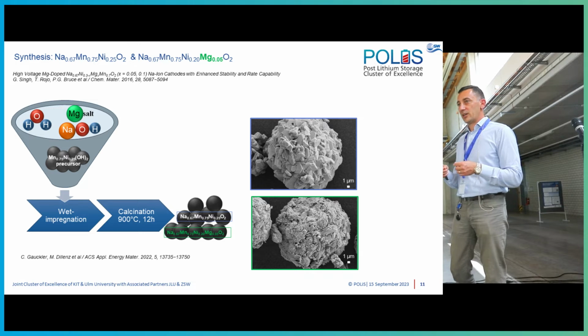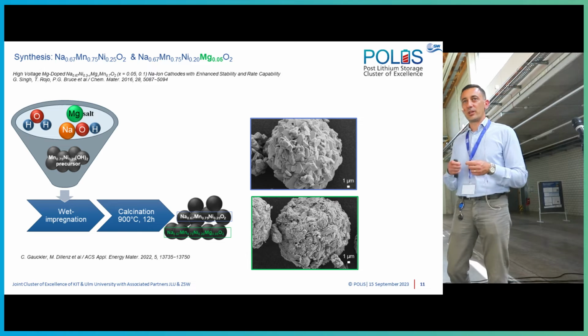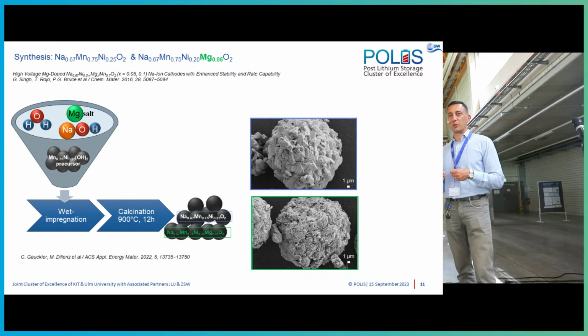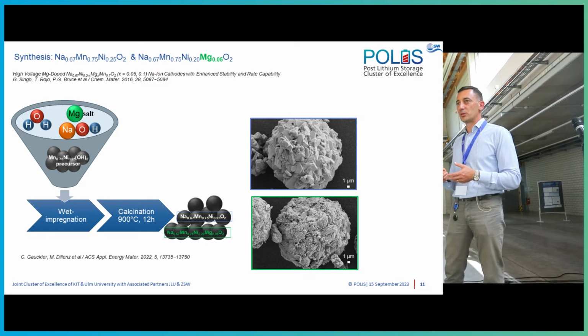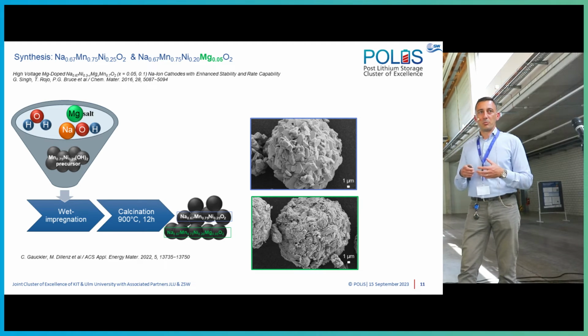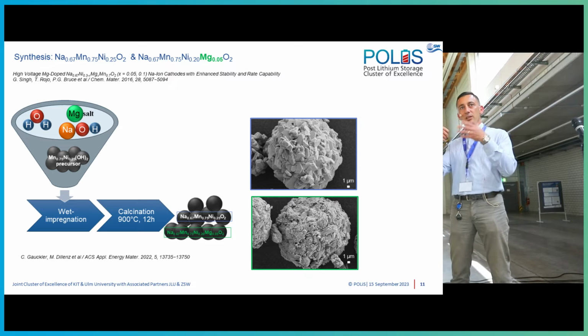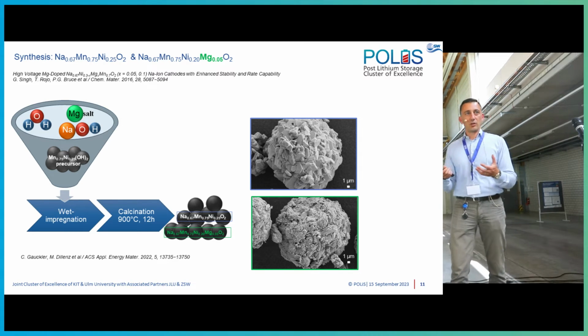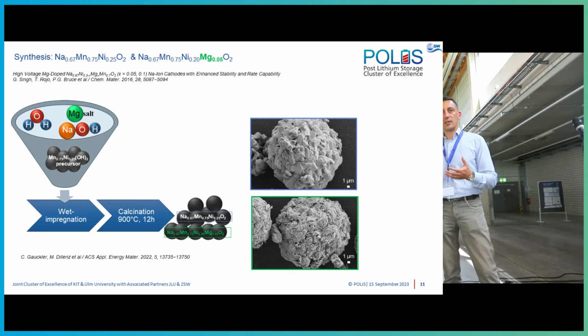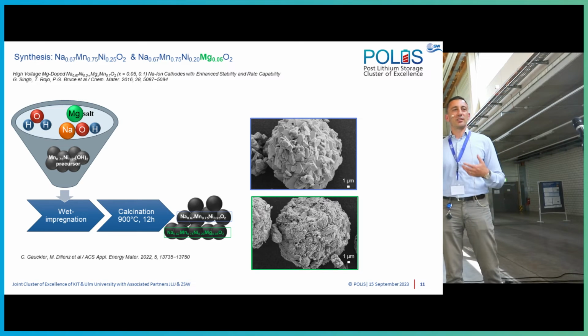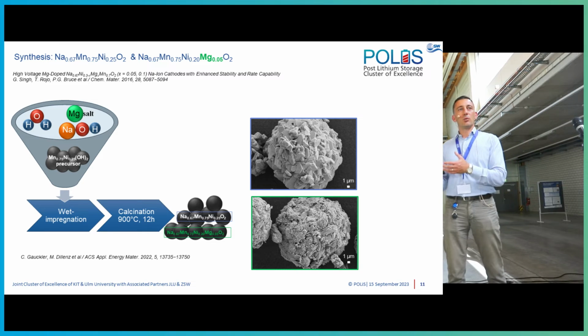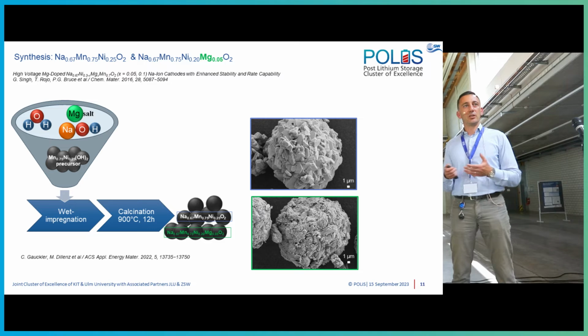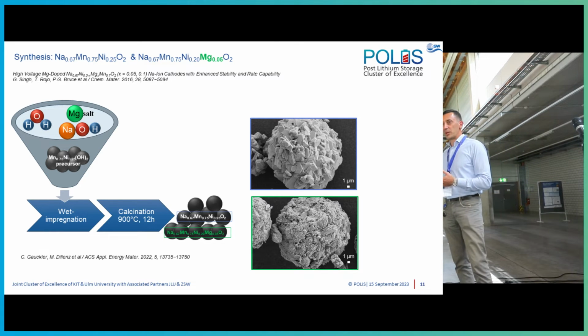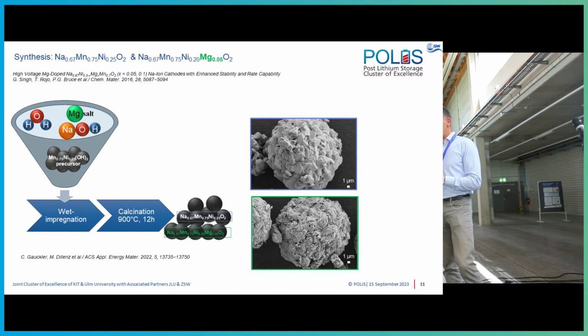Why am I saying as well? We have seen before from Julian, if you are familiar with coating technologies and materials for lithium-ion batteries, you will see that most of the materials have a spherical particle architecture, so with small crystallites, but then aggregates and secondary particles that are in the micrometer range. This gives you an edge in terms of handling of the material when you think about producing gigawatt hours of cells, but this is also what we can do in our pilot lines, where we manage 100 kilos of material per batch. So you don't want to have very small particles flying around. This is one thing. Usually, spherical particles have better flowability. They pack more densely, so you get more tap density, and so on.